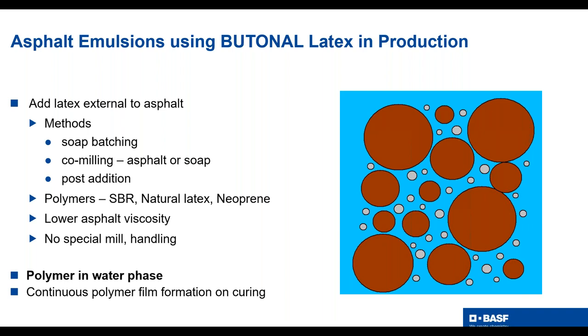And what you're looking at is, again, the latex is part of the soap solution. When you make the emulsion, it is co-milled, which means if you look at the picture on the right, it's kind of a picture of the asphalt droplets, which are fairly large compared to the latex droplets. And the latex droplets are separate themselves. And there'll be a couple of slides later, which I'll show you basically how this coalesces and forms, and actually a picture of a mixture that kind of proves this concept of this latex film.